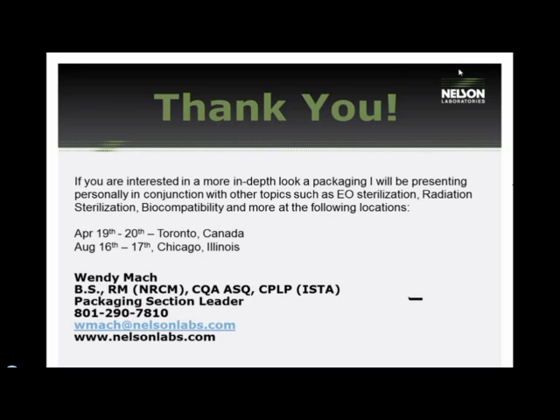Can we use manufacturer's data of microbial challenge to waive this test in a package performance validation? Absolutely, provided that the data that you use is representative of your product. Frequently, I refer customers that do gamma sterilization to find out this data from the manufacturer. It's a little more difficult when you're referring to ethylene oxide sterilization because the parameters are so different depending on density and things like that. So trying to replicate exactly what the manufacturer has used is difficult. But absolutely, if you can get that and find it representative, you can use that.